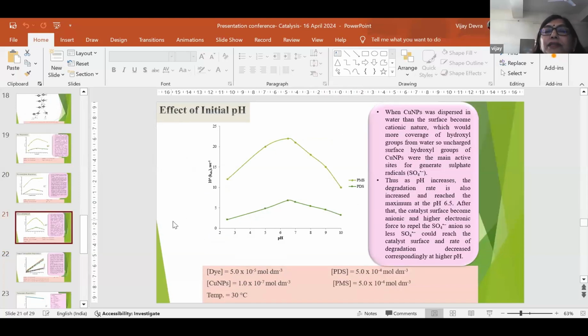Now, the effect of the initial pH. When copper nanoparticles are dispersed in water, the surface becomes cationic in nature, which would give more coverage of hydroxyl groups from the water. So uncharged surface hydroxyl groups of the copper nanoparticle were the main active sites for generating sulfate radicals. Thus, as pH increases, the degradation rate also increases and reaches the maximum at pH 6.5. After that, the catalytic surface becomes anionic and has a higher electrostatic force to repel the sulfate anion. So fewer sulfate radicals could reach the catalyst surface, and the rate of degradation decreases correspondingly at higher pH.